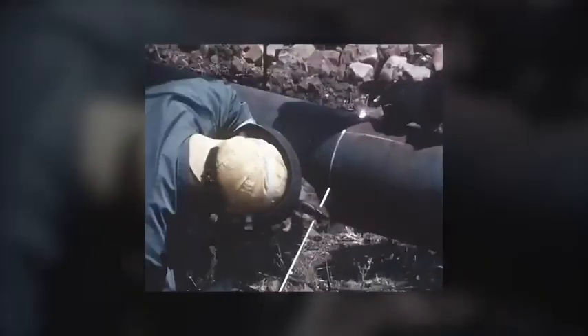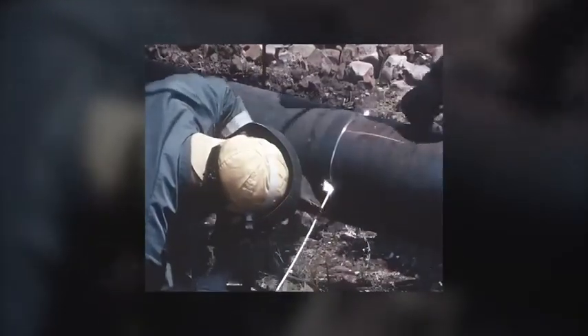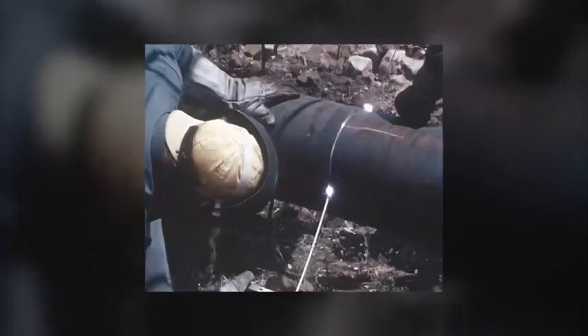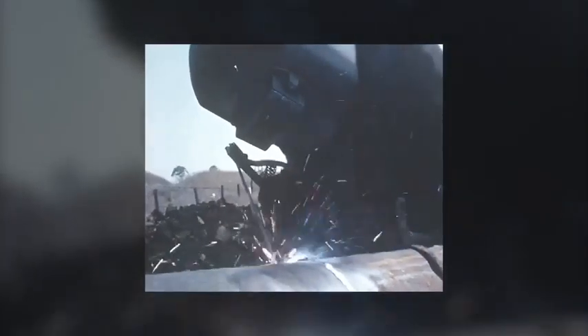The welding operation was carried out in 3 phases, using an electric arc to melt and fuse the metal to the pipe joint. The electrodes were coated with a substance to reduce oxidization and form a shield of slag at the weld. First, a stringer bead weld. Then, grinding. Then, an intermediate, followed by a final capping weld.